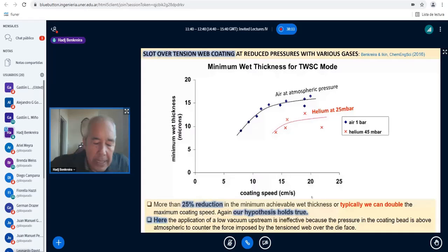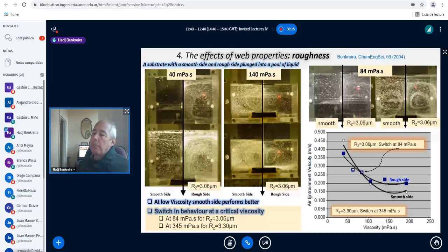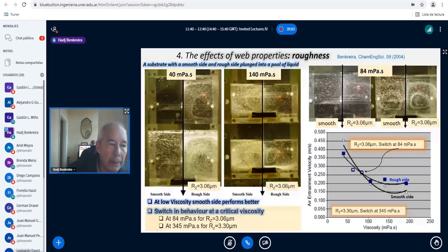So as I said, the next thing, therefore, was to look at the property of the substrate itself, very close on the surface. And when you look at the property of the surface, what we did, we used our dip coater and we plunged a substrate that had a smooth side and a rough side into a pool of liquid. And you see here is the substrate plunging. On this side it's smooth, and on this side is rough. And then observe that at 40 millipascal seconds, the rough side entrains air much sooner than the smooth side. So at 40 millipascal seconds, the smooth side performs better.